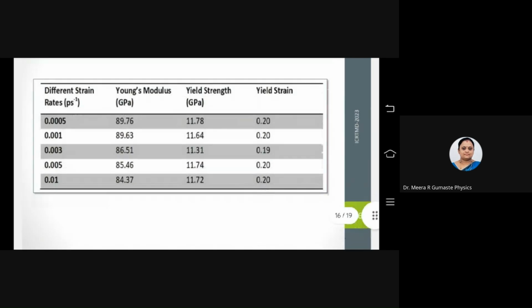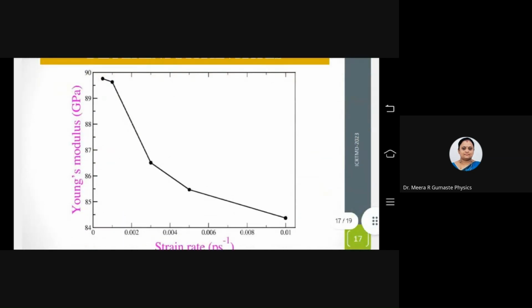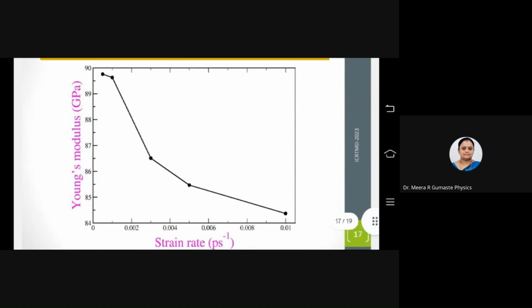So in this table I am presenting the Young's modulus, yield strength and yield strain with respect to the strain rate. So we have noticed that the Young's modulus decreases marginally with increase in strain rate, but the yield strength and yield strain remain constant. So here I have plotted the Young's modulus with respect to the strain rate, and it shows clearly that there is a decrease in the Young's modulus with increase in strain rate.